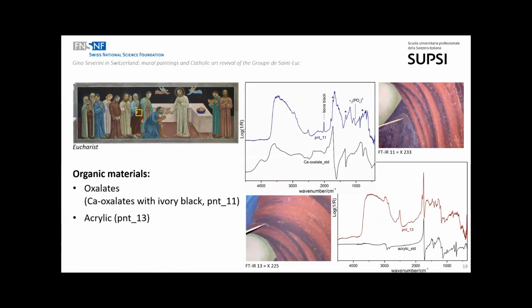In this wall painting it was also possible to identify the presence of degradation products like calcium oxalate. These products are generally formed by oxidation processes of organic materials. So this could be an indication of the presence of a possible organic material degraded over time. And also the presence again of acrylic, retouching from a later conservation treatment.